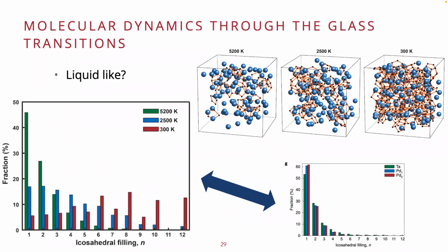I think it's kind of in the middle, meaning that we did perform our own molecular dynamics simulations. What we did find was that yes, you can actually have pentagonal bipyramids that are very highly dense, which correlates really highly to having a system with high numbers of icosahedra. But in our experimental data, it actually looked more closely like a high temperature melt, right? Which begs the question, well, is our